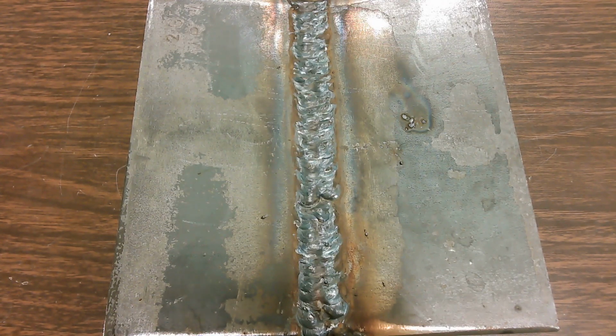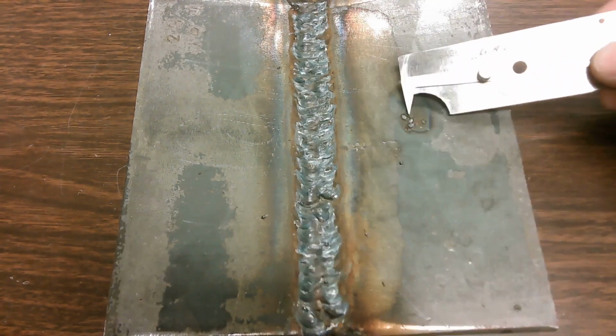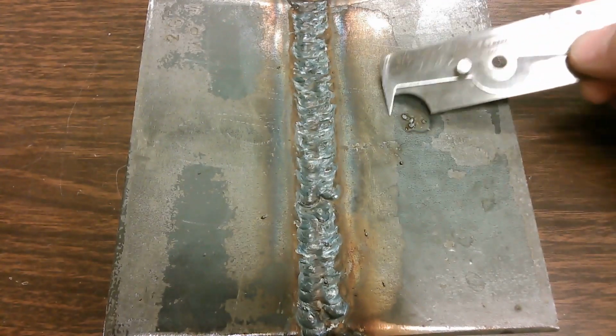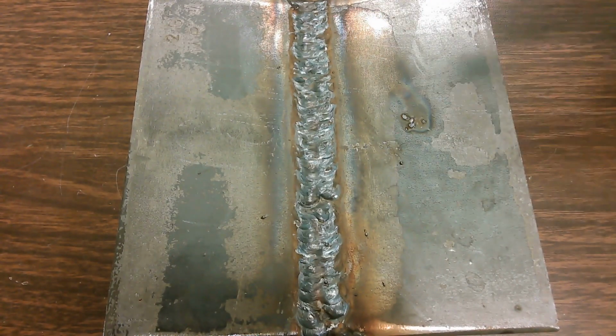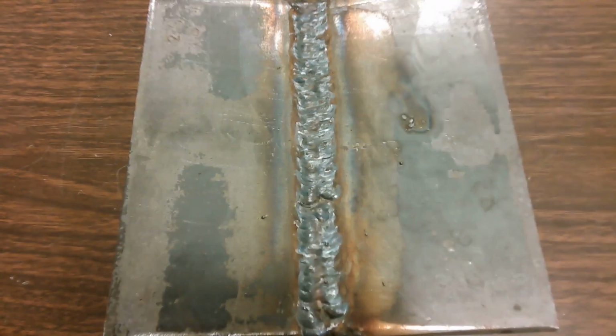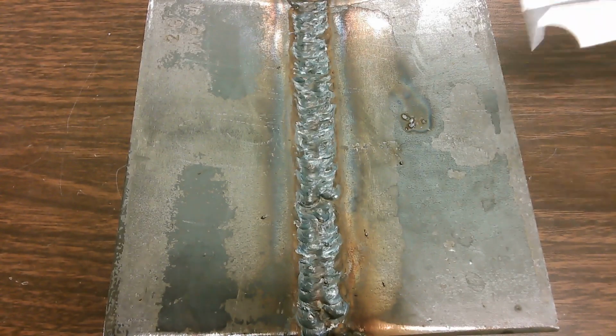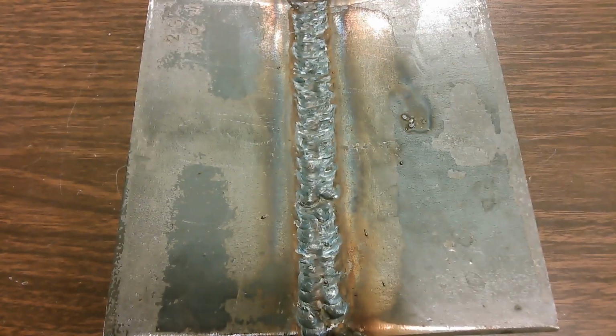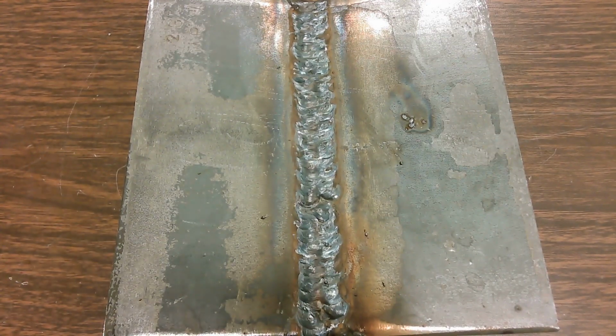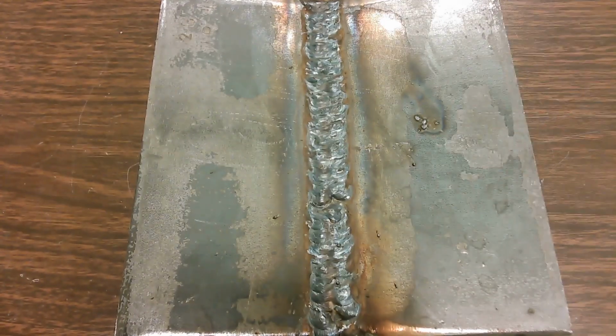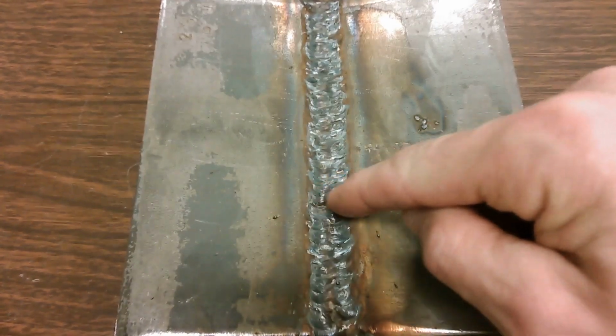So anyway, this is a 3G weld, and I pointed this one out for a couple reasons. One, we've got an arc strike here. So again, you could sand that with a flap disc and get those marks out so it looks like bare clean metal. But if you were to do that and then take an acid etch and etch over the top of that, you would see a heat affected zone in there. Again, we're changing the grain structure of the metal in that spot, so that's a bad thing. The other thing I want to show you is this is a weave weld, versus stringers. Stringers would be small narrow beads stacked next to each other versus weaving the electrode back and forth.